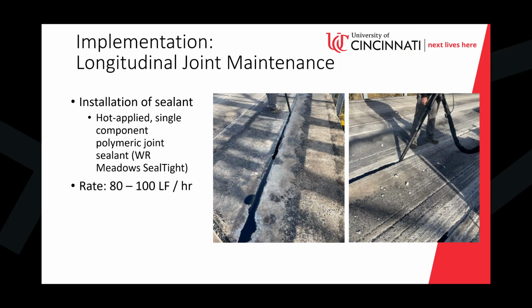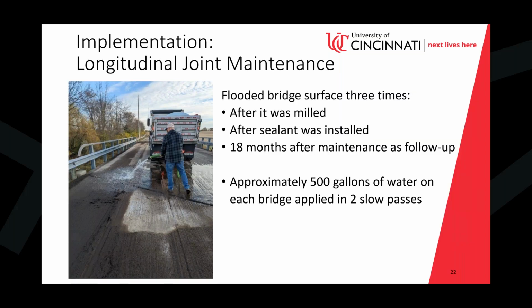And we wanted to monitor its effectiveness. So it's not just looking at it being done, what's the cost associated and the time and the equipment and all, but was this an effective means of repair? And so what we did is we flooded the bridge surface. We did it 3 times. We did it after the top was ground out or milled. We did it before the sealant was in place. Then we did it after the sealant was installed.